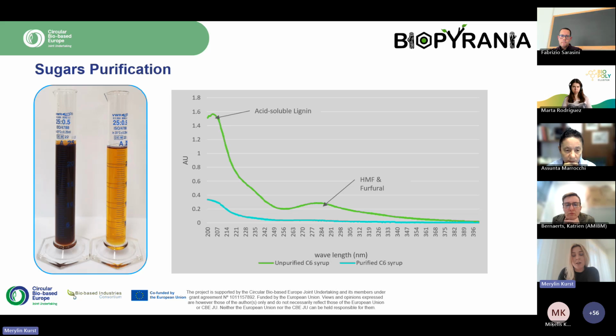The primary reason for the dark color is the presence of lignin, which contains aromatic structures that strongly contribute to coloration. There are several different purification techniques available, for example, adsorption via activated carbon or polymer resins, membrane filtration, ion exchange, and so on, but it all comes down to purification cost and demand. If we remove acid-soluble lignin, HMF, furfural, organic acids, then it directly affects the fermentation, for example. Microbes are sensitive to organic acids, HMF, lignin, and furfural. Also, catalysis impurities poison catalysts, and the final product quality is also improved.